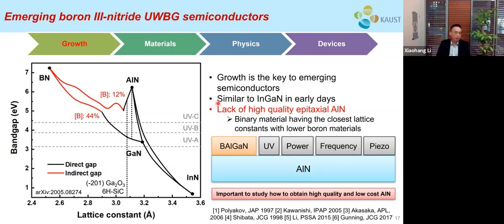For indium gallium nitride at that time, there was a lack of high quality epitaxial gallium nitride as a substrate. For boron aluminum nitride and boron gallium nitride, there is a lack of high quality epitaxial aluminum nitride. Aluminum nitride is chosen here to be the ideal template or substrate because it has the closest lattice constant, for reduction in the strain and cracks.